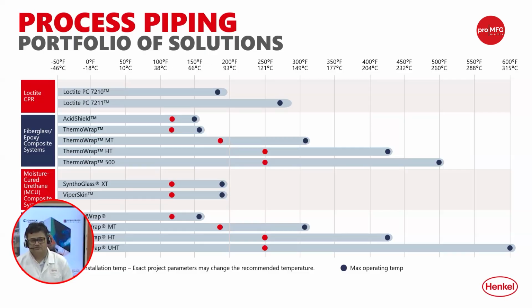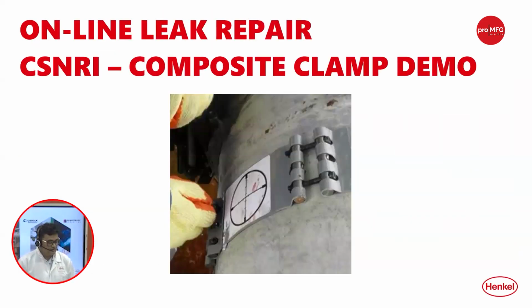There is another system we call Diamond Wrap, which is again based on epoxy and carbon, and it can work up to 315 degrees centigrade. So it is a big portfolio to cater to different applications and challenges, to increase the life of the asset. On the fiber side, normally we work with carbon fiber, glass fiber, a mix of carbon and glass, and also basalt fiber. In terms of the engineering polymer matrix embedded in the fibers, that is mainly epoxy and polyurethane. So these are the overall systems and solutions we provide to increase the life of the asset.